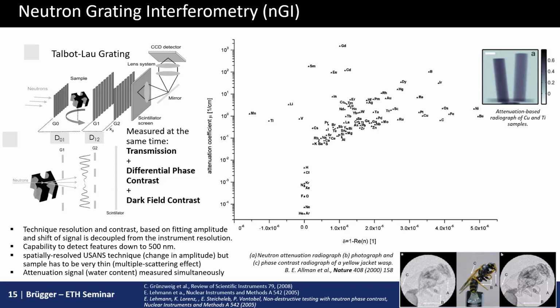But with gratings, we can do interferometric measurements of that very small angle on top of just doing the normal imaging. So here now, we can actually map, again, spatially, for example, if you want to look at porosity in the field of, say, 50 microns, you can build a grating, or actually just tune a grating that is multichromatic, to actually then see those points of porosity. And again, you're superimposing this onto an imaging product. So you actually have a picture of the sample and you say, oh, here is my defect area, and I'm going to have failure in this area before I have failure elsewhere.